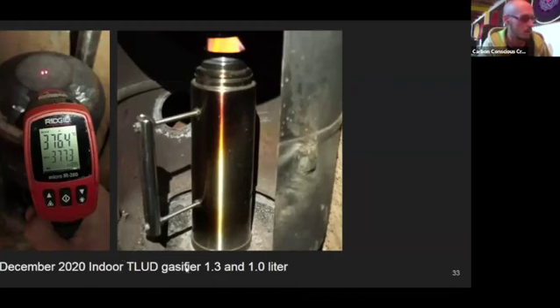And then I actually made a couple of extra cylinders also in 1 liter. So I could regulate the temperature on the cook plate based on which gasifier I was using. For example, if I was cooking a soup, I would start it with the 1.3-liter gasifier, which would bring the water to a boil. Then when that was finished, after an hour or so, I would switch it to the 1-liter gasifier to maintain a soft rolling boil. So I could do a soup that was boiling for a couple of hours. And that gave me some flexibility with the heat output.